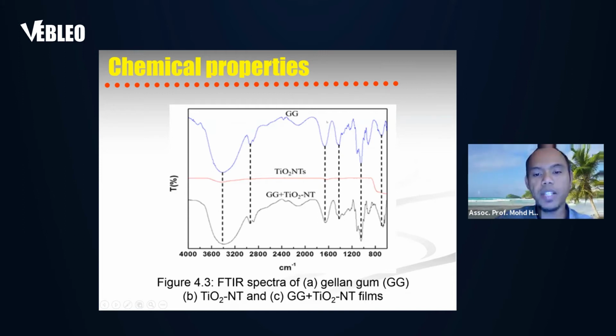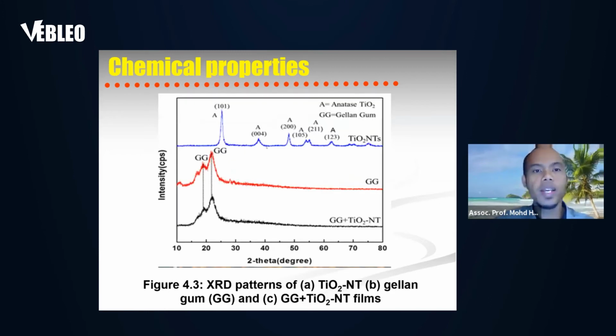Okay, we can see the pattern of the FTIR spectra. This is the main functional group for both samples. We can see the presence of titanium dioxide nanotubes. And this again is the XRD pattern of titanium dioxide nanotubes. This titanium dioxide nanotube belongs to anatase TiO2. And then we have Gellan gum patterns, this GG, the pure GG film. And this is where we incorporated titanium dioxide into the GG film. All right. So basically, we can hardly observe the titanium dioxide pattern in GG plus titanium dioxide nanotubes, since we only use very small portions of titanium dioxide nanotubes in this film.